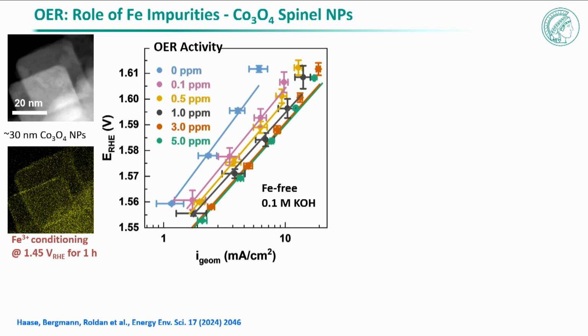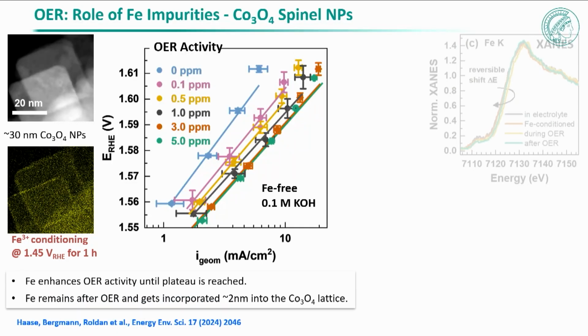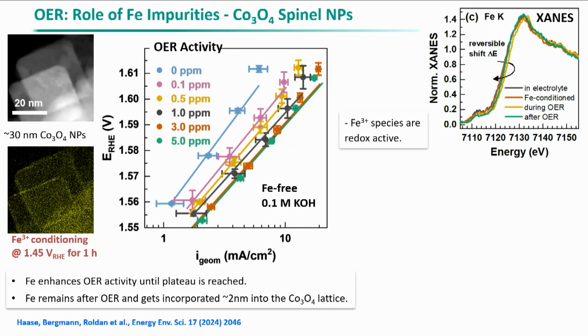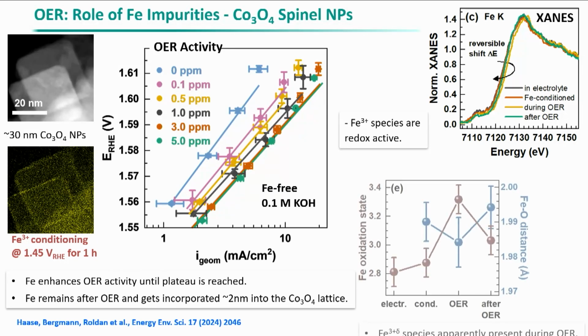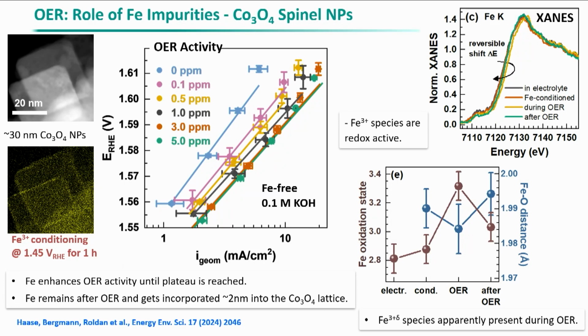And at the beginning, if you look at the performance, this is here the current density, our activity, and you go from no iron in the electrolyte to iron in the electrolyte, you see that the catalyst becomes better until you get a stable state. So if you think about this, first of all, you need to see if the iron is doing something, and we see actually that the iron is doing some redox cycle here, so the iron is part of the active species. And we can see also that under OER conditions, oxygen evolution reaction conditions, the iron oxidation state is also changing. So that means that it's not just a spectator, the iron is doing something in our system.